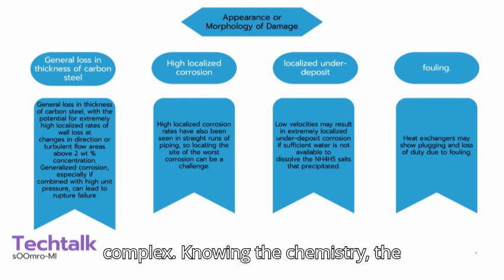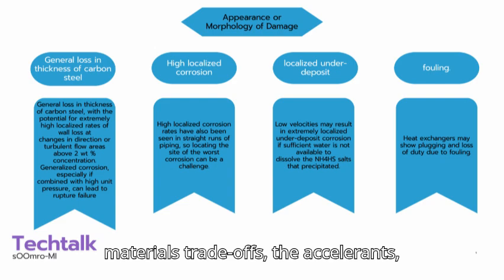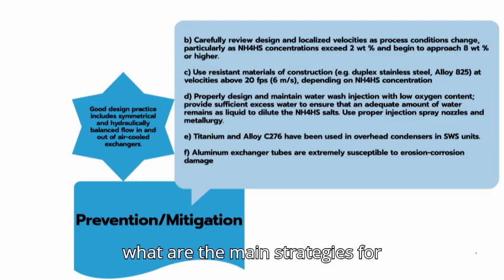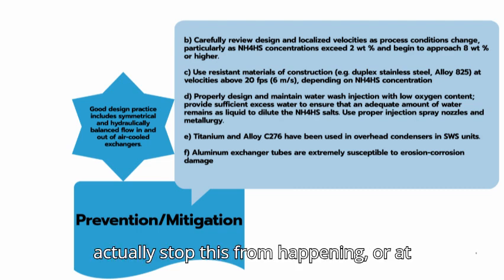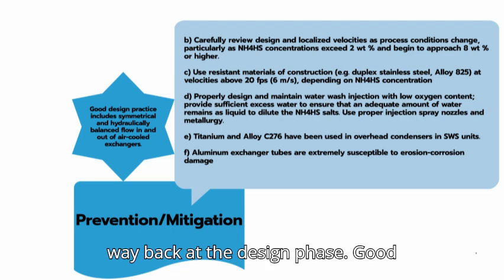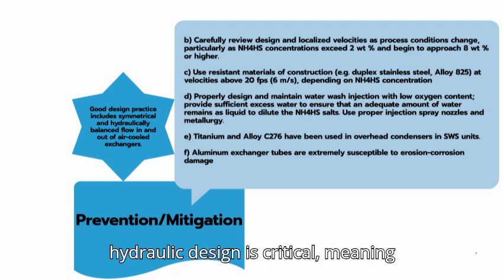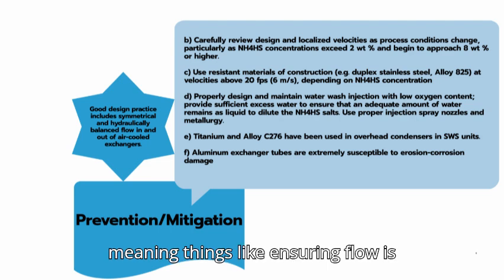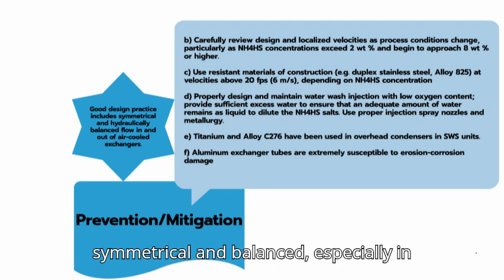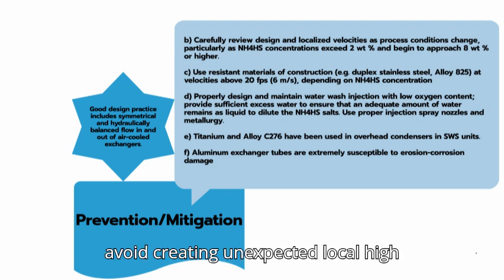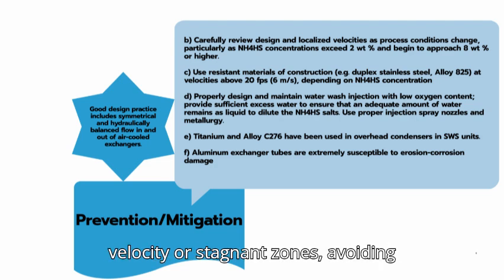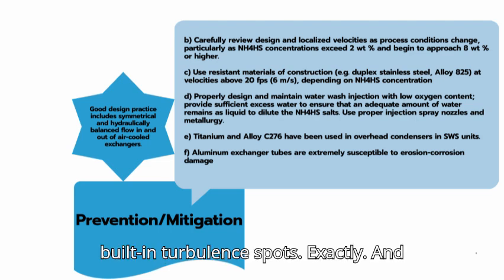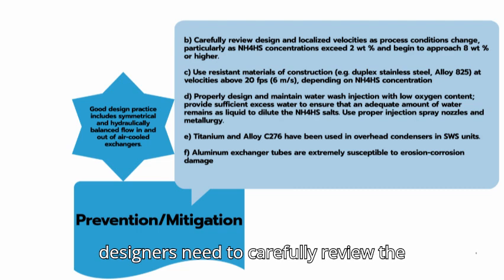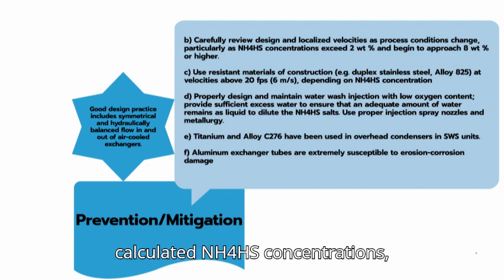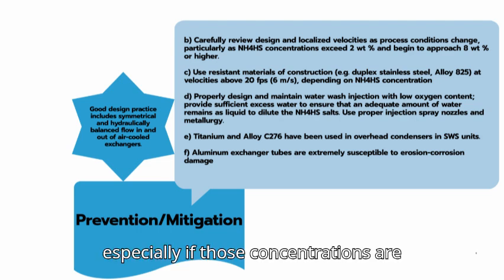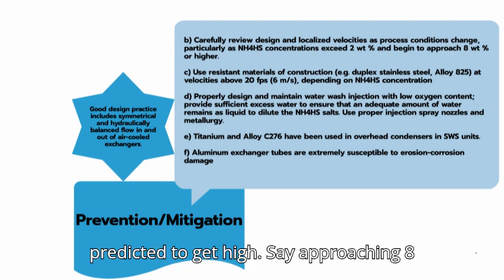Okay, this is complex. Knowing the chemistry, the materials trade-offs, the accelerants, what are the main strategies for prevention and mitigation? How do we actually stop this from happening, or at least control it? Well, it really starts way back at the design phase. Good hydraulic design is critical. Meaning? Meaning things like ensuring flow is symmetrical and balanced, especially in heat exchangers like air coolers, to avoid creating unexpected local high velocity or stagnant zones. Avoiding built-in turbulent spots. Exactly. And designers need to carefully review the expected localized velocities and the calculated NH4HS concentrations, especially if those concentrations are predicted to get high, say approaching 8 weight% or more.